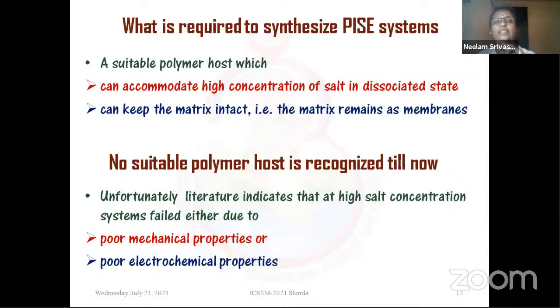And what is required for this PISE system? The polymer host should be good enough to accommodate a very large amount of the salt and keep it in the dissociated form. It is not only accommodating the salt, but keeping it in the dissociated form. At the same time, it can hold a large amount of the salt and keep the matrix flexible enough. The problems which have been recognized till now, if you go through the literature, you will find that whenever you try a PISE system, either you end up with poor mechanical properties because too much salt is making the matrix a little bit brittle, or the salt association is taking place. So ultimately your electrochemical properties are not good enough.